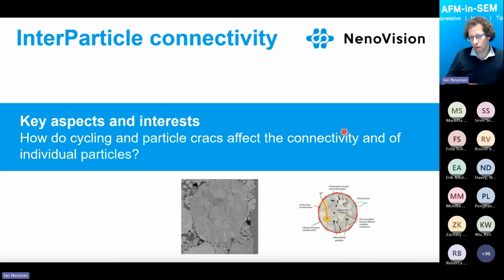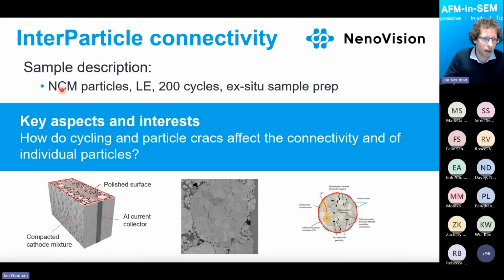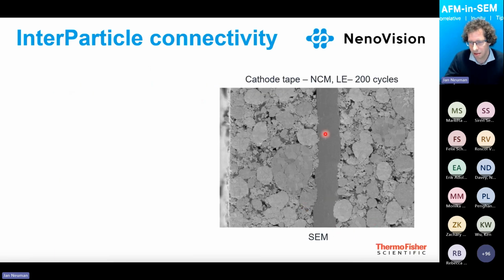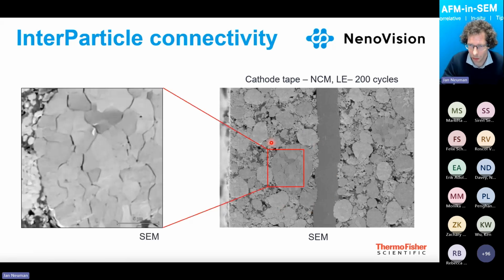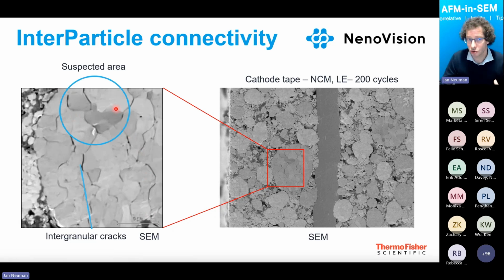Another point of view which I would like to highlight is interparticle connectivity. As we were discussing, the particle is breathing during the cycling and cracks are appearing. So the question is, how do cracks affect the connectivity inside the cathode itself? For that experiment, we use NCM particles, liquid electrolyte after 200 cycles, which means the cracks are already there. This is how it looks. So again, you can see the collector, and you can see nicely the particle which we have selected for the analysis. On this SEM image, you can already see the cracks, which are visible, and also areas which show a different contrast in the electron microscope.